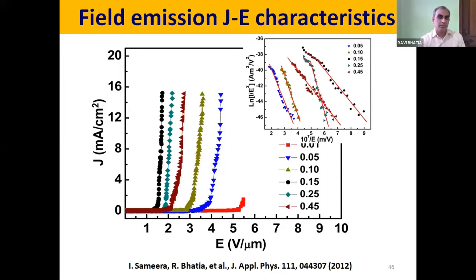So this was further examined: we need to find out if this data really follows the Fowler-Nordheim equation or not. So there has to be 1 upon E, and the equation which we have already seen. The straight line curve shows that the field emission in this composite follows the Fowler-Nordheim equation.